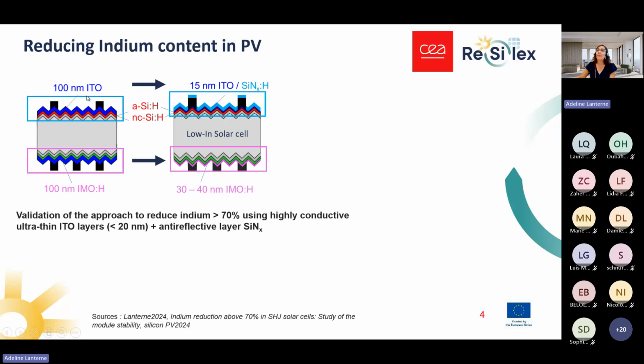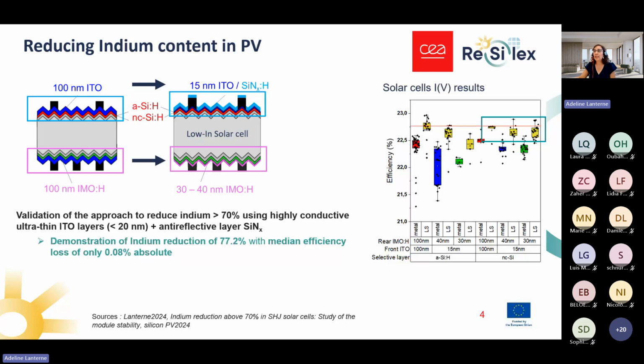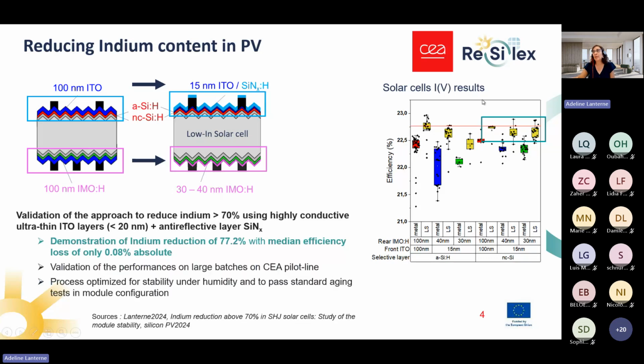here, we reduce its thickness from 100 nanometers to 15 on the front, and we combine this with a silicon nitride layer to keep very good anti-reflection properties. And thanks to this, we optimized this in the project, and we reach a point where we have near no efficiency losses with a 77.2% indium reduction in content. We have only 0.08% absolute of efficiency losses, and we could validate this in the project on large batches on the CEA pilot line, and the process was also optimized for having good stability under humidity, and also optimized so that we could pass a standard aging test in module configuration.